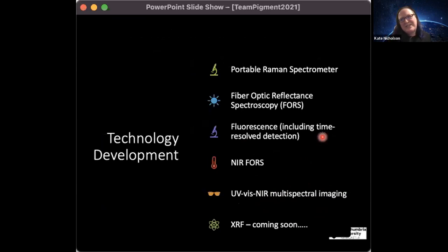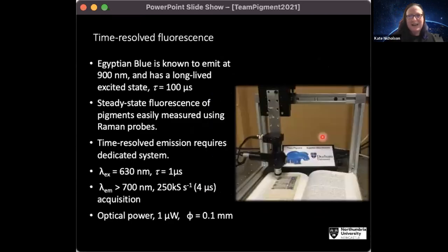But just seeing fluorescence there, it's not quite enough proof. To prove what your pigment is by fluorescence, you need its fluorescence lifetime, how long it emits for. And Egyptian blue emits for a very long time. So again, I went back to the lab, had a little bit of an argument with Andy, and magically an Egyptian blue detector appeared.